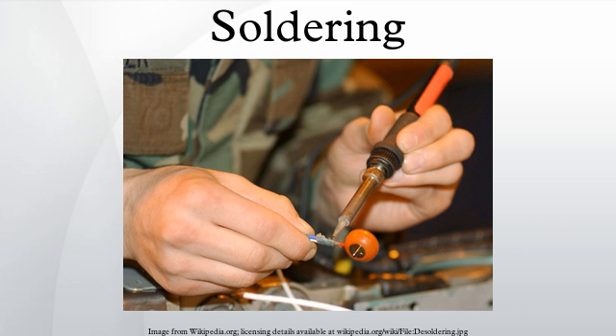Since copper pipe quickly conducts heat away from a joint, great care must be taken to ensure that the joint is properly heated through to obtain a good bond. After the joint is properly cleaned, fluxed and fitted, the torch flame is applied to the thickest part of the joint, typically the fitting with the pipe inside it, with the solder applied at the gap between the tube and the fitting. When all the parts are heated through, the solder will melt and flow into the joint by capillary action. The torch may need to be moved around the joint to ensure all areas are wetted out.